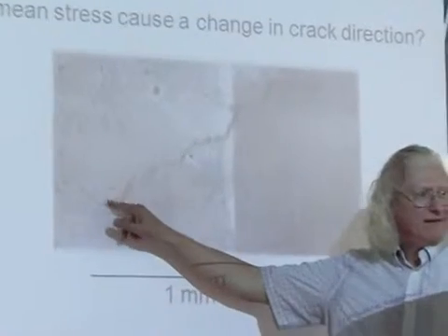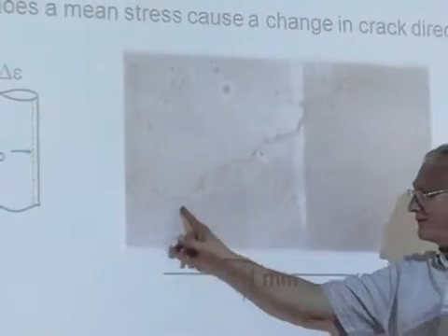This is the idea that there can't be a universal theory, because materials will do what they do. Cracks turn from these shear cracks, and they grow into tension when they get bigger. You can see this happened after it got to be about 1 millimeter. Right? And it can hang on for a while as it's growing like this. And of course, when it's growing like this with this mode 1 crack at the end, nothing happens. Nothing happens.